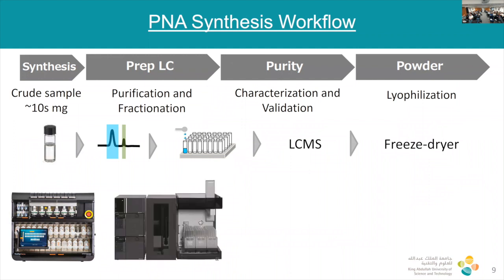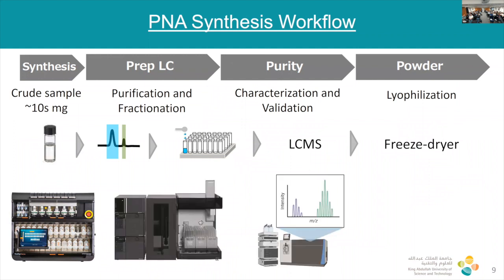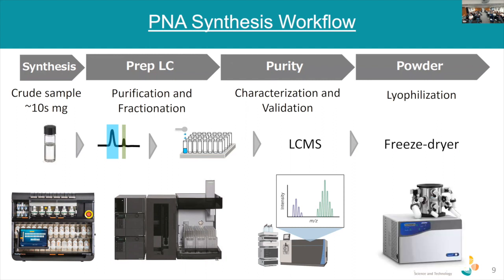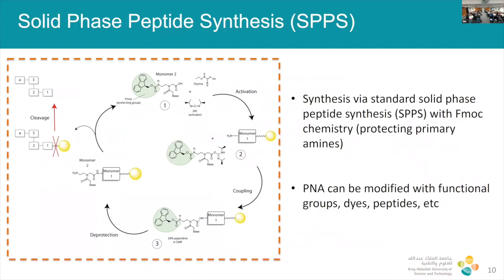We then purify with HPLC. We do some mass spec to confirm that we've got the right oligo synthesized, and then we freeze dry it. Very quickly, the synthesis, how does it work? It's exactly the same as solid phase peptide synthesis, where you have a resin, and then you're adding monomers one by one through activation, coupling, and then deprotection of the big protecting group, FMOC. And then you repeat that cycle over and over again until you get your oligo.